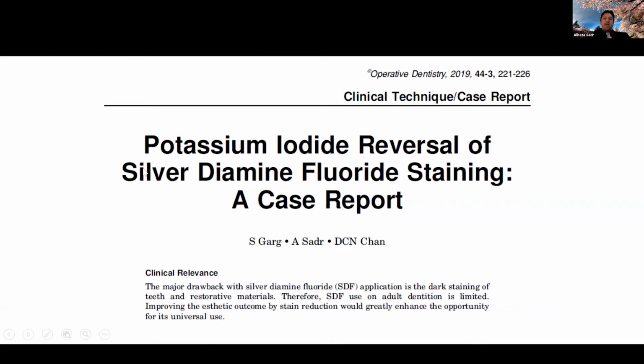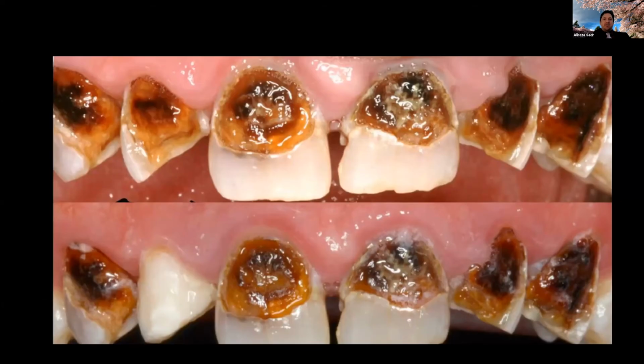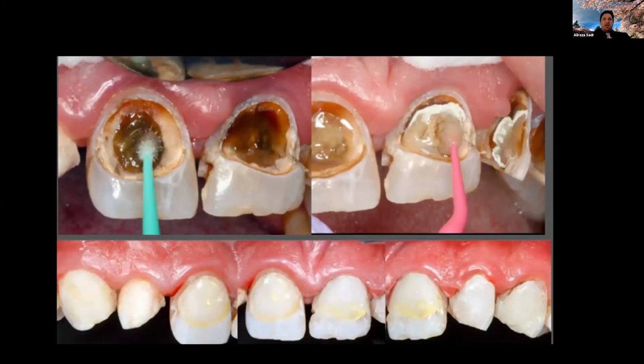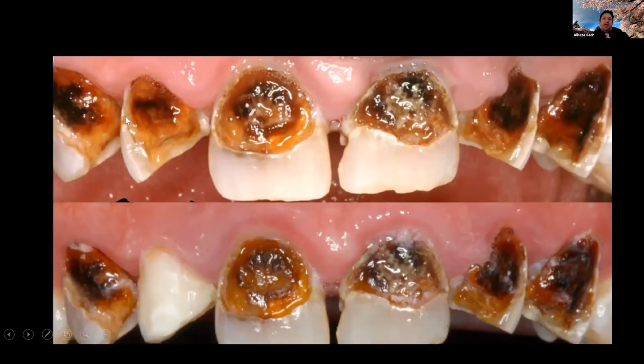One of the ways that we can tackle these kind of cases is with the silver diamine fluoride. So what we just cleaned up very lightly. Why do we clean up here lightly? Because we of course want to remove the biofilm as much as possible here. You could use air abrasion in these cases, but you've got to be very careful with the potential exposure of the pulp because it could happen very fast.